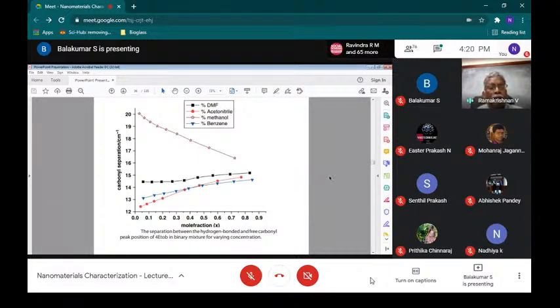So the separation between the hydrogen bonded and the free carbonyl group, because you have shown the isotropic component and the anisotropic component, you have two peaks. In isotropic, one strong peak and a shoulder, the other is equally so. The separation between the two components varies with the various solvents. When the solvent concentration increases, the separation decreases. In other cases, it shoots up.